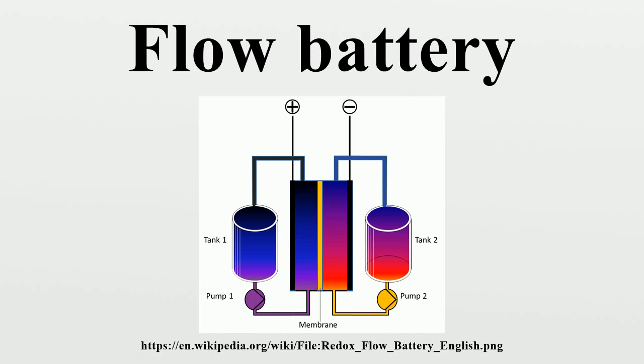Polymer. A novel flow battery concept that is based on redox-active organic polymers and dialysis membranes was announced in 2015. The polymer-based redox flow battery uses functionalized macromolecules dissolved in water as active material for the anode as well as the cathode. Thereby, metals and strongly corrosive electrolytes, like vanadium salts and sulfuric acid, are avoided and simple dialysis membranes can be employed. The membrane, which separates the cathode and the anode of the flow cell, works like a strainer and is produced much more easily and at lower cost than conventional ion-selective membranes. It retains the big, spaghetti-like polymer molecules, while allowing the small counterions to pass.